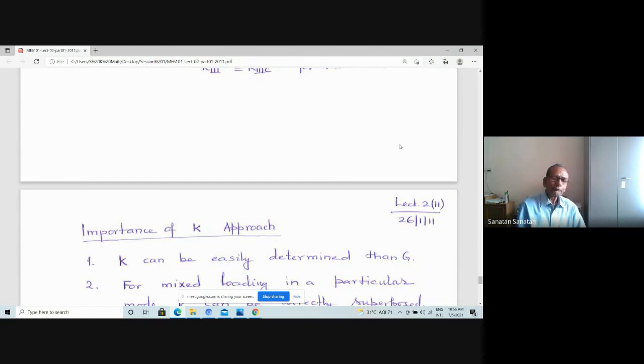So in the presence of a crack, the stress field is very complicated. But the stress near the crack tip is infinity. So one cannot really talk of failure in terms of stress and strain as we used to think about. But Irwin could show that the energy required for crack extension is fortunately related to the multiplier of the first term, which is proportional to r to the power